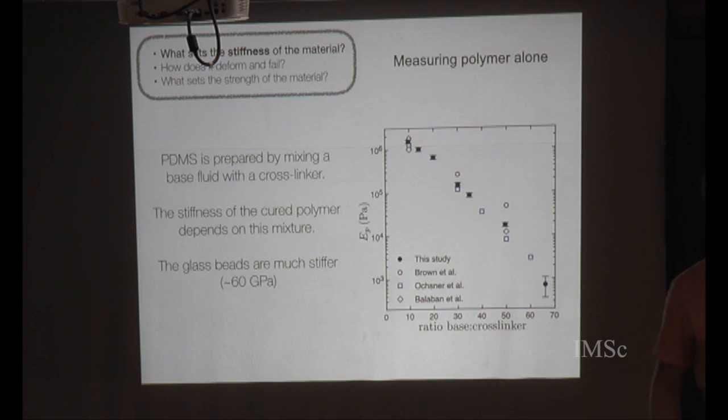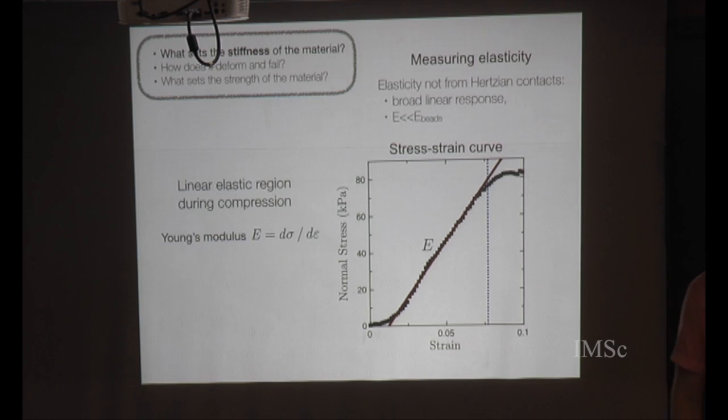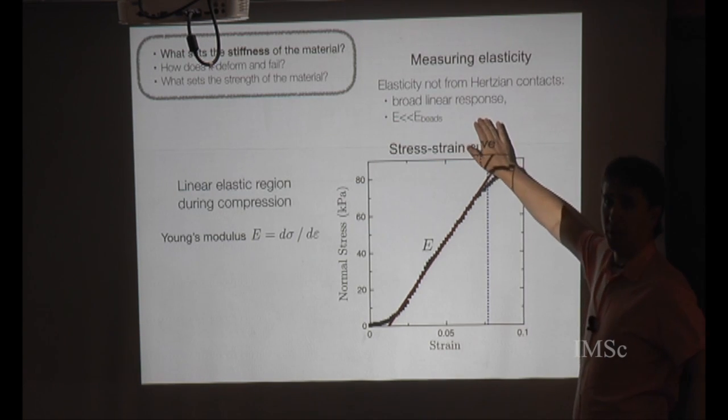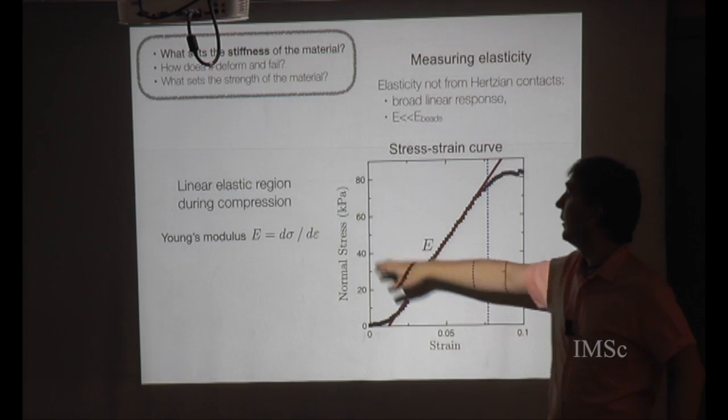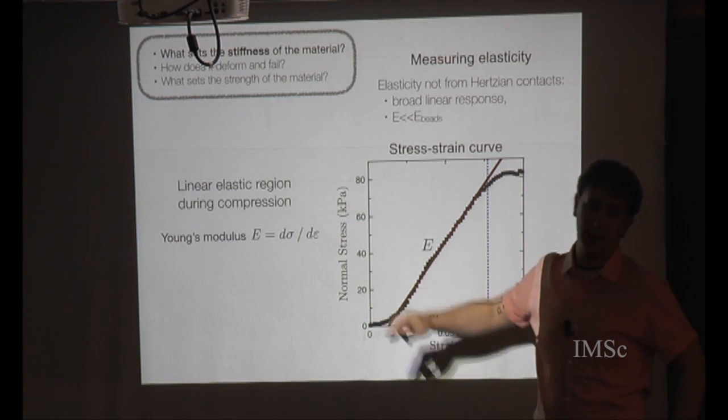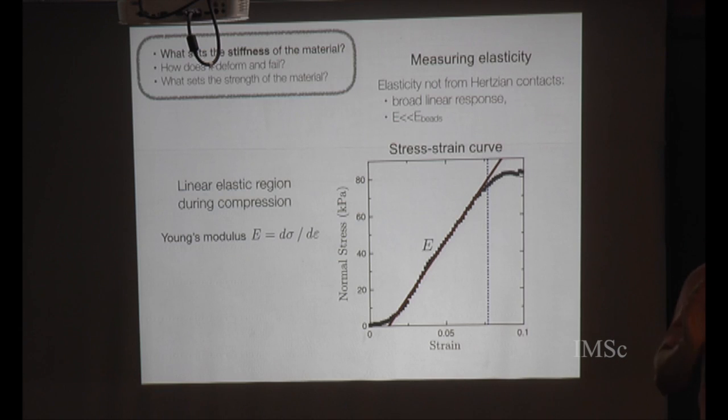So where were we? Right. The one key point here is the Young's modulus of the beads is measured in gigapascals. The stresses we're talking about here are kilopascals, and the elastic modulus of these materials is kilo to megapascals. So we are dominated largely by the softer phase, despite the polymer occupying typically about 1 to 3% of the volume fraction. It is dominating the physical response.